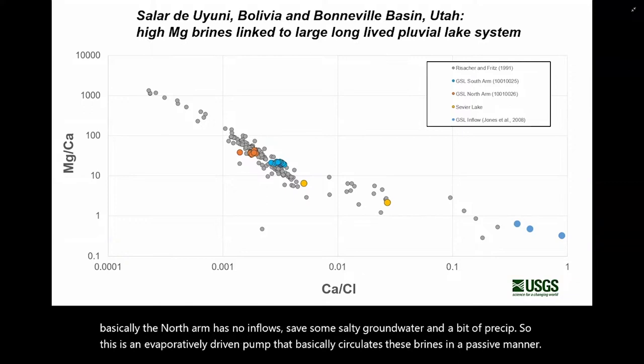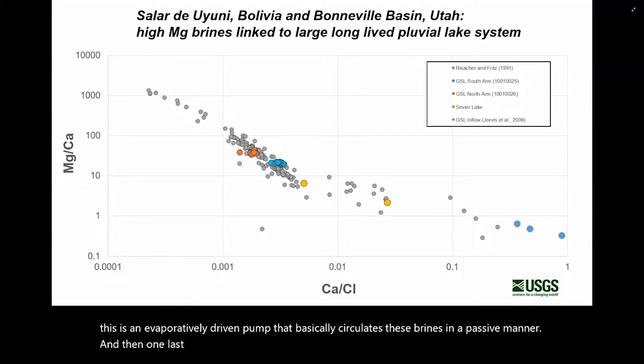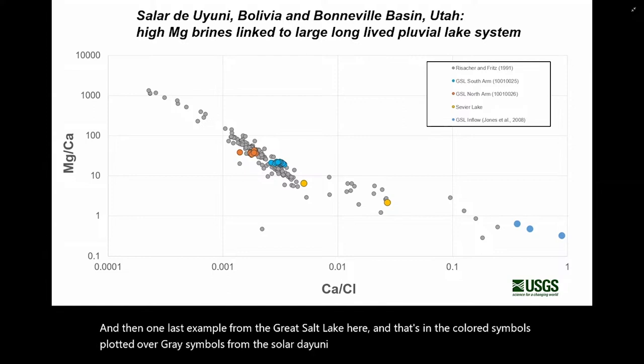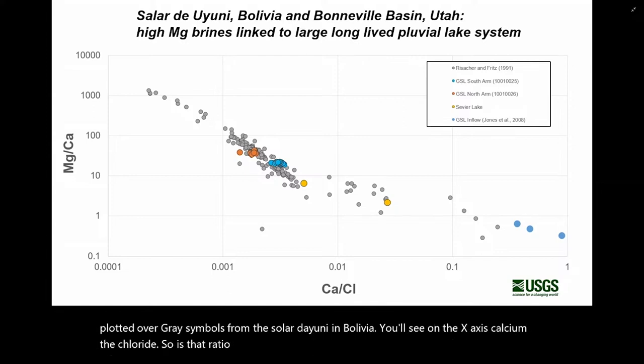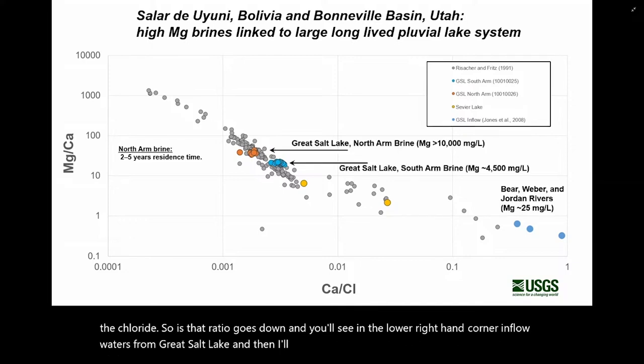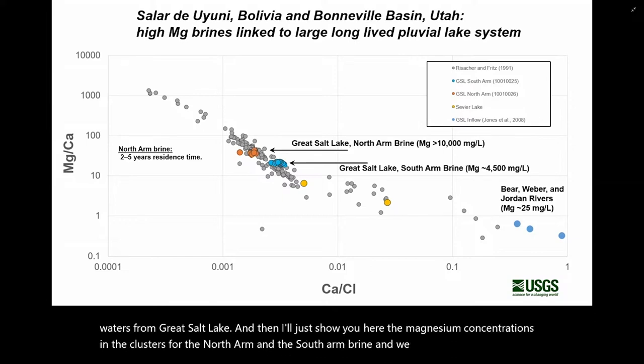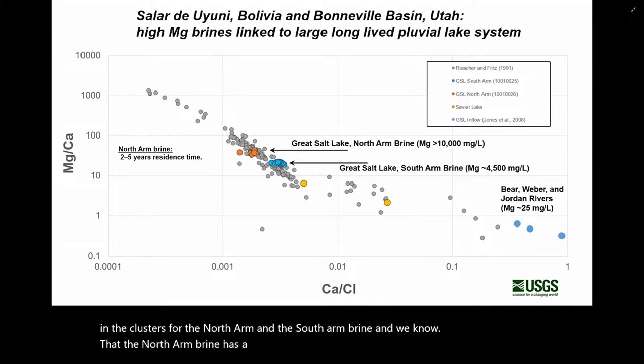And then one last example from the Great Salt Lake here, in the colored symbols, plotted over gray symbols from the Salar de Uyuni in Bolivia. You'll see on the x-axis calcium to chloride. As that ratio goes down, and you'll see in the lower right-hand corner, inflow waters from Great Salt Lake. And then I'll show you here the magnesium concentrations in the clusters for the north arm and the south arm brine. And we know that the north arm brine has a residence time of 2 to 5 years based on measured flows and the known volume.